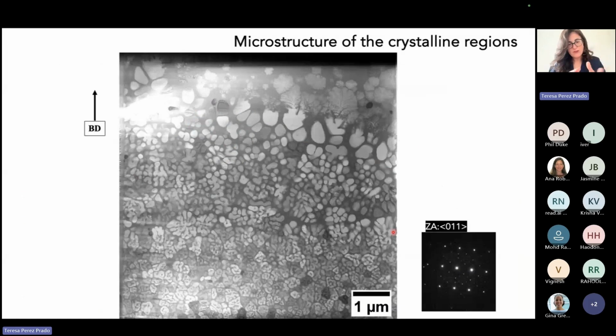We also went further. We zoomed in more by TEM, and you can see here an image of the crystallites. The melt pool boundary would be here, and here are the crystallites in the heat-affected zone surrounding the melt pool.